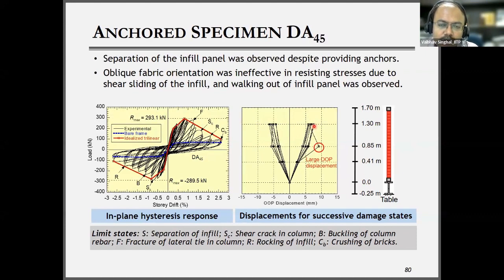And this is the response of a specimen which has the fabric at an angle of 45 degrees. So this specimen gives us the maximum strength because generally the tendency you will see, when the masonry is present in the RC frame, is that loads are transferred primarily through a diagonal. So when the loads are transferred diagonally, definitely the oblique or 45 degree placement of the fabric will take better forces, or you can say the distribution of forces will be better in the fabric, and that is why they have taken the maximum strength.